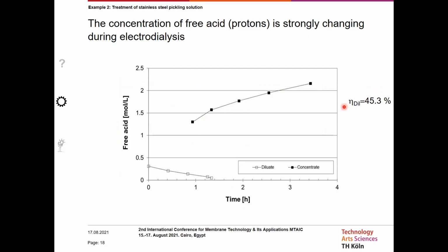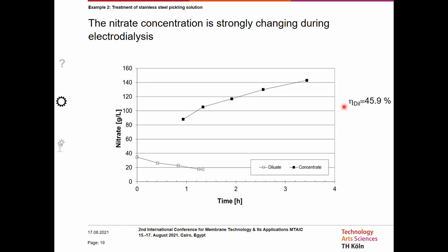Here we can see that the efficiency was in the range of 45%. That means 45% of the electric energy that was supplied to the stack was transferred into the ionic transport. Then we can have a look at the nitrate concentration. Here the behavior is quite similar. The nitrate concentration was rising more or less linearly with the time. And also in this case, the current efficiency was in the range of 45%. So this was what we could expect.